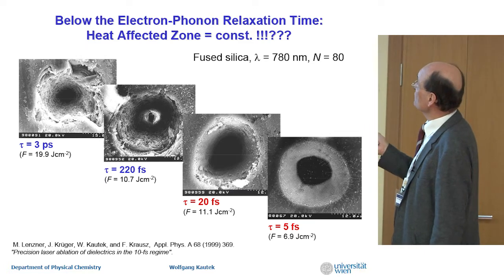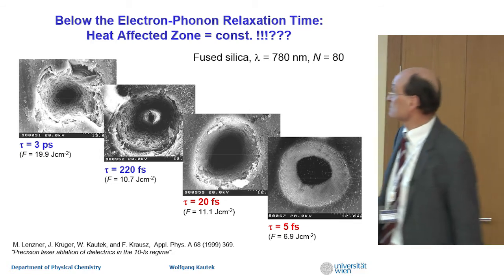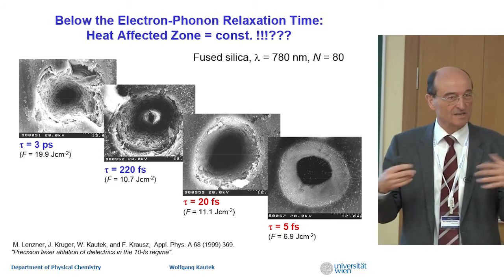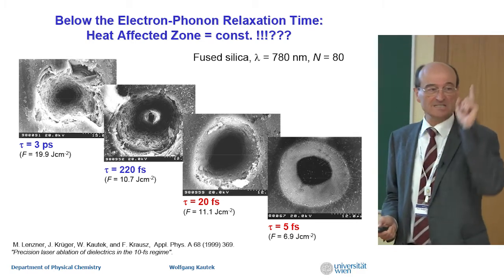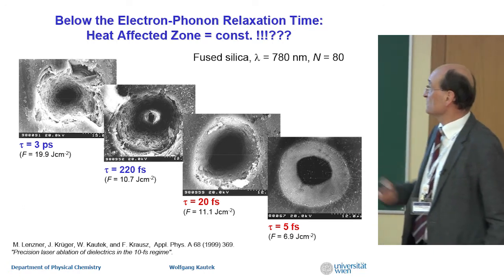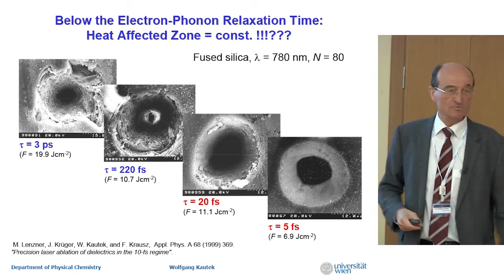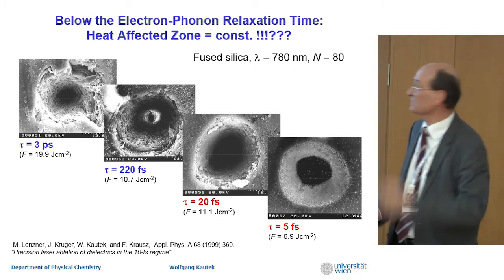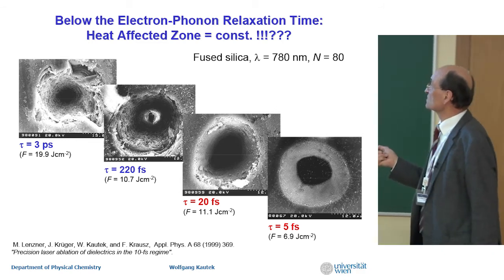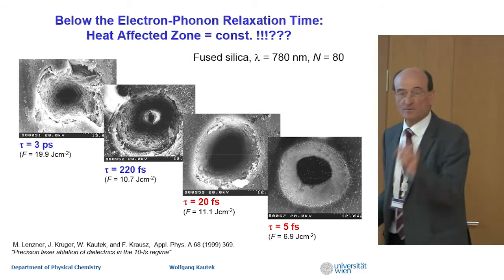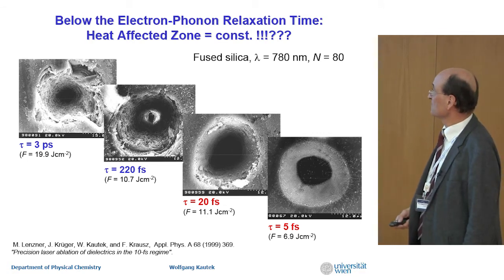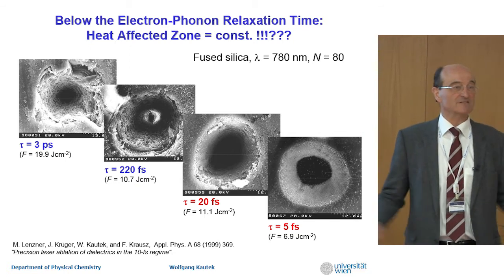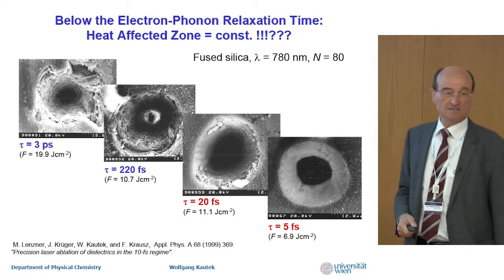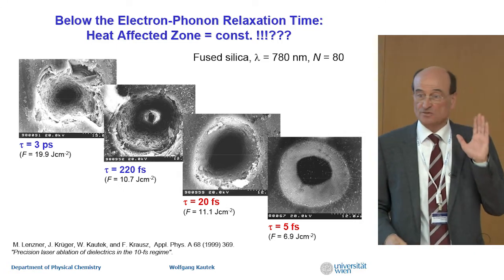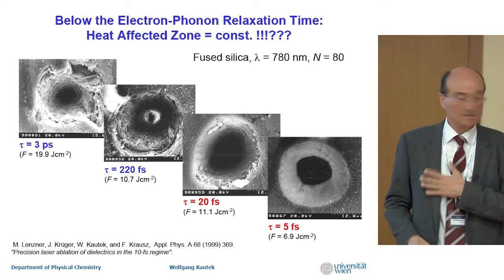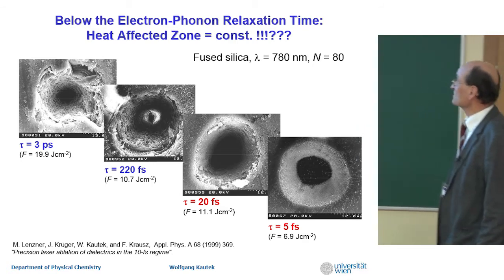Look, for instance, that is a fused silica ablation, 3 picoseconds. It looks quite bad. There are a lot of splintering and so on. If we shorten the time or increase the intensity, then at 220 femtoseconds, it got a little better. That was state of the art for decades, you know, hundreds of femtoseconds. Then we shortened to 20 femtoseconds and it improved. And then we went to the shortest pulse possible, and it was better even. So by increasing the intensity, we could change below the time of electron phonon relaxation. We could improve the quality. We didn't understand that. Now, a short explanation comes in this picture.